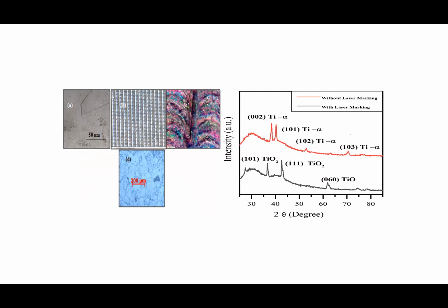We went for laser marking and studied the microstructure behavior. The marking was done on a titanium plate, and the microstructure before marking had alpha Ti and the presence of beta Ti lamellae in the intergranular region. The as-received microstructure suggested that the titanium plate underwent a cold roll process, because the plates which we procured from outside had some cold roll behavior, which resulted in some change in microstructure. The average grain size varied between 350 micrometer to 250 micrometer and 50 micrometer to 100 micrometer.